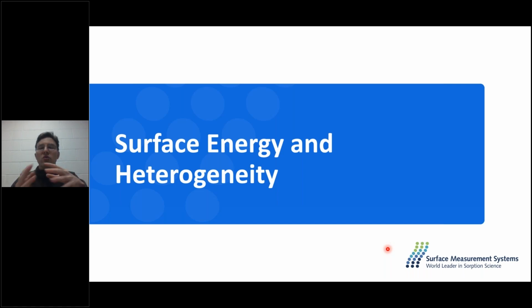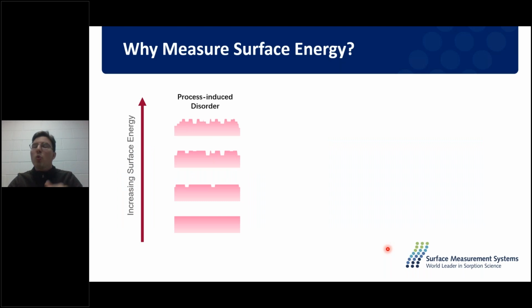So we can measure our surface area in an inverse and we then calculate the surface area. We plug in that known surface area back into the instrument, and then we now know the surface of our sample in the column. That means the software knows how much of our probes to inject to achieve a certain surface coverage. And it's with those surface coverages that I can make a surface energy profile. But why do I want to know surface energy?